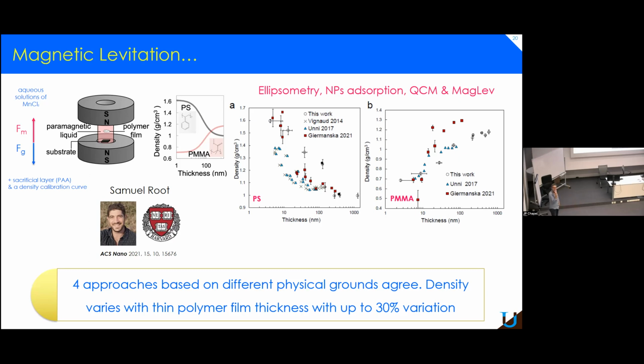I didn't do the experiment myself. I read the paper many times, but he didn't mention that. The only thing that I know is that, as we did, we relaxed the chains by heating close to the dissolution. We remove any trace of solvent. We release any stress that was inside, and after that we do the measurement. In this case, frankly, I cannot answer your question.